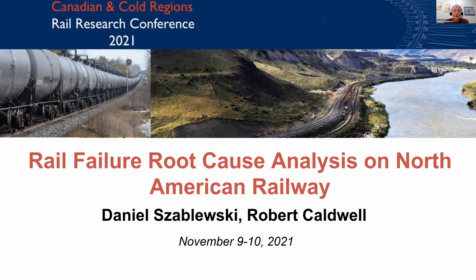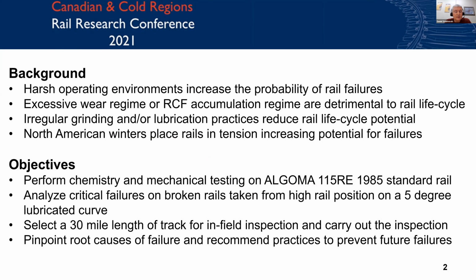So today we'll be looking at the rail failure root cause analysis on a North American railway. As a background, there are very harsh operating conditions. The harsh environmental operating conditions increase the probability of rail failure. There are two different regimes that cause this to happen. You either have the excessive wear regime or the excessive RCF regime. Either one of those destroys the rail running surface and causes cracks to initiate, propagate, and then lead to critical failure. And that's obviously detrimental to the rail life cycle.